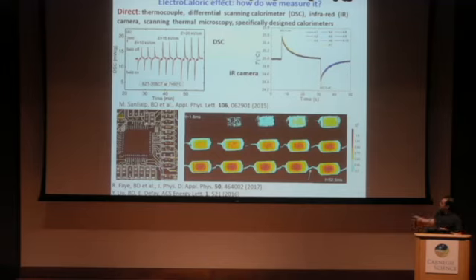and with time we see that there is a heating of this MLC device. So once again, you start at a given temperature, you apply the electric field, then you have an increase of the temperature. The heat is released to the environment, then you go back to the initial temperature, you switch off, and then you have a decrease of the temperature. And of course, you may cycle this many, many times.